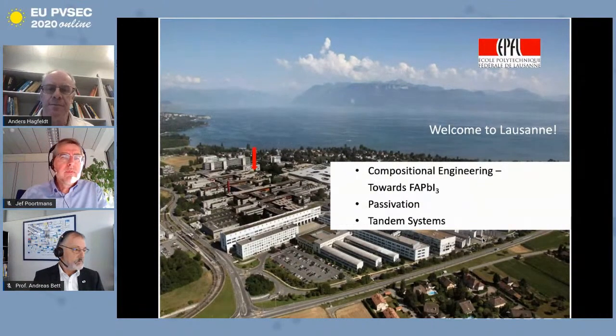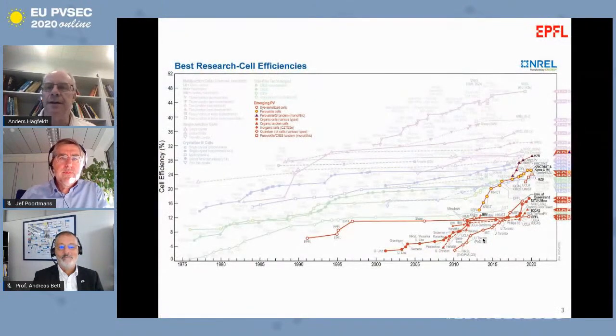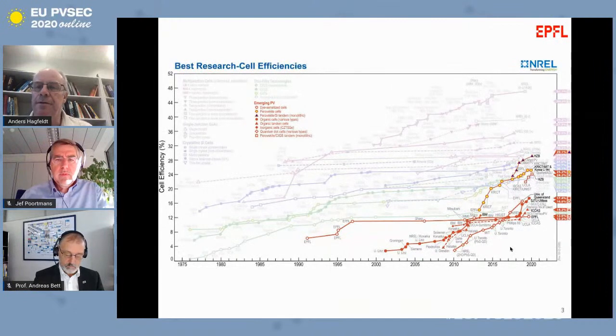And on the tandem systems, which I will finish and then more or less hand over to other talks where we will see record levels and so on. So if I start with the classic chart, you can go to the right-hand side of the chart, and you will see then that the certified record is by the Korean KRICT and MIT at 25.2. We have then the tandem device, which is by the Helmholtz Center in Berlin, 29.1. And there is also from the same group the record for tandem on perovskite on CIGS. So that's in terms of efficiency, small devices, of course, but the certified values.